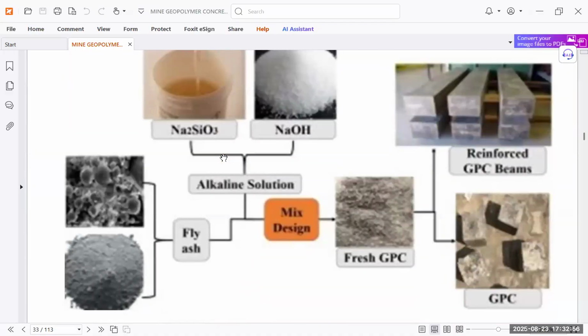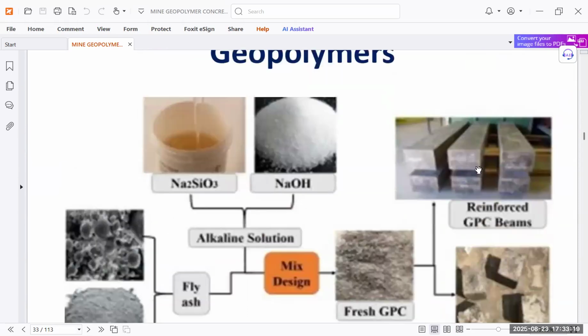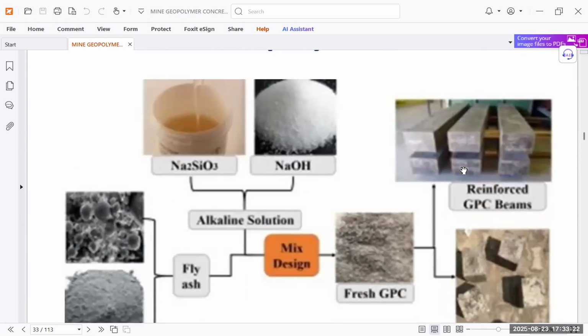And then geopolymers are something like this. When we make this, you can see this Na2SiO3 plus NaOH solution there. This will be used to make the alkaline solution, and fly ash also we will take from here. Then alkaline solution plus fly ash we will mix. Then we will get the mix design, and then fresh GPC will be made. This fresh geopolymer concrete will be used for making the cubes and reinforced GPC beams also. So this is the way by which we can produce geopolymer concrete, and we can use it in RCC beams also. These will be called reinforced GPC beams because we are using geopolymer concrete in them. Similarly, geopolymer cubes are made like this. These are the things by which we go for geopolymer concrete.